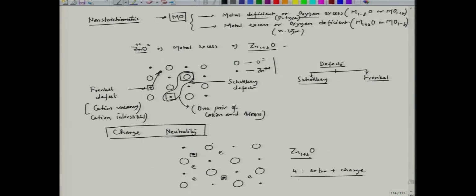Now, that is why it is called n type. Why? Because here the electron becomes my charge carrier. And of course, the interstitial position is filled with that excess zinc ion. So, this interstitial position can exchange, and that way the zinc ion will move through the oxide layer. That means it is diffusion through the interstitial, and the charge carrier would be electron. So, this is a kind of n type oxide. Like that we can also explain other oxides, whether p type or n type.